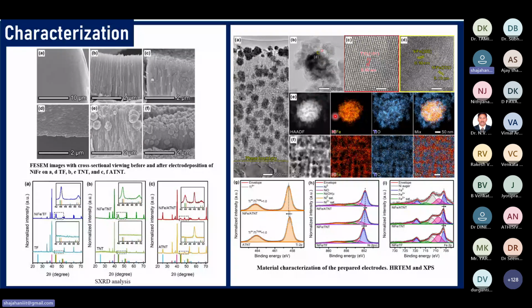When we analyzed individual nanoparticles by cutting using the FIB technique, we observed that the nanoparticles formed are porous in nature. That is obviously helpful for better hydrogen escape, better water electrolysis, better flow of electrolyte, everything will be helpful. XPS analysis we also carried out, which also confirmed successful formation of nickel iron nanoparticles on the corresponding ATNT substrate.